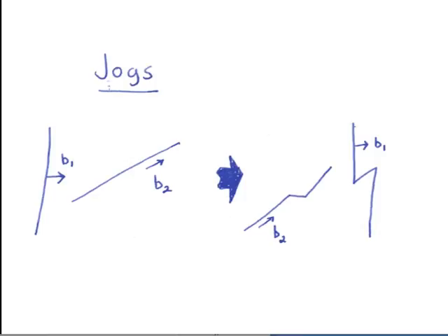Now, what was originally a screw dislocation here has now acquired an edge component, because the Burgers vector is constant along the line vector, right? And therefore, originally the screw could glide on any plane containing its line vector. Now it cannot do so. So when dislocations interfere, you will render them sessile. They won't be able to move. So the second condition for a martensitic interface is that it can only contain one array of dislocations, right?